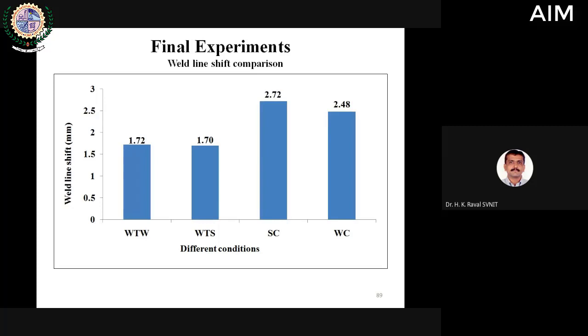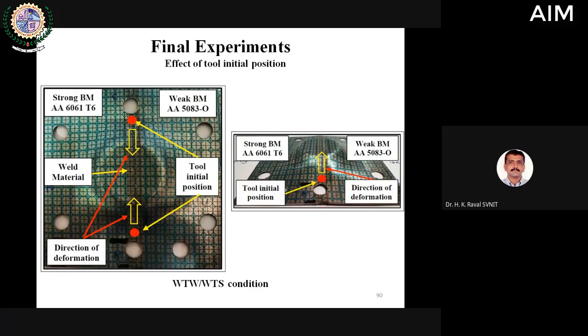And simulation results also show a similar trend, where WTS and WTW give the minimum weld line shift, minimum thinning, and minimum plastic strain. So experimental findings and simulation findings are in the same trend. We cannot have an exact comparison of the magnitude. As I told you earlier, parameters are supposed to be accurate to conduct the simulations. These are the additional images just to have more validation of the experimental findings.